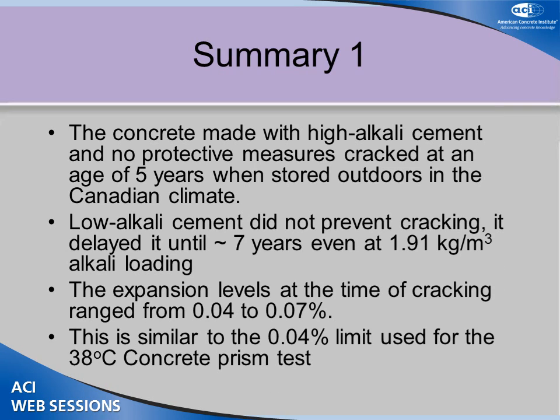I will just summarize what we found. We got cracking within 5 years in the field with this high-alkali Portland cement concrete when it was outdoors. Low-alkali cement started to crack at about 7 years, even though it had a much lower alkali loading with this aggregate, so it wasn't sufficient to protect it.